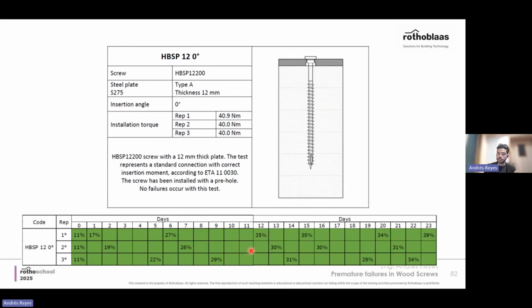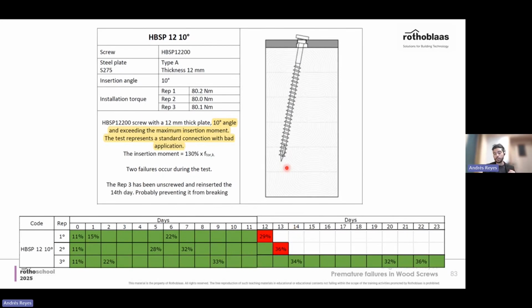But it's very interesting because even if environmental hydrogen embrittlement could have been an issue in this case, because there's moisture, there's stress, and there could be a core hardness susceptibility of the material, they didn't break because the stress side was not enough. It wasn't enough for them to break. While in this case, it could have been as well that with the improper installation angles, with the bending of the screw, you start having some cracks and you start letting corrosion happen.